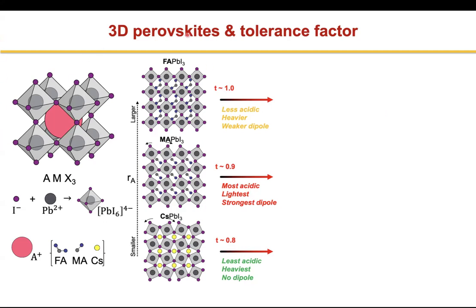So perovskite is a type of mineral, and it forms this ABX3 structure, where A is your cation, and this is typically a monovalent cation, things like formamidinium, methylammonium, or cesium. It's got a +1 charge. Then I have a metal in the center, which is the B, typically things like lead or germanium or tin, and that has a divalent, 2+ charge. And then I have the halides, which are at these apical sites. These are the X, which is iodine, bromine, and chlorine, and that's an anion. And so when I mix these things together, I can form a halide perovskite.